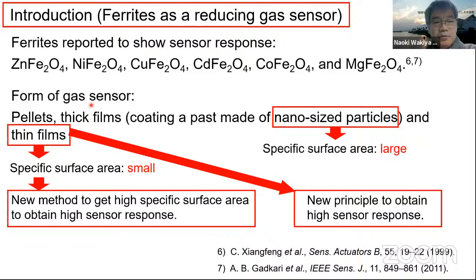And ferrites are reported to show sensor response, such as zinc ferrite, nickel ferrite, copper ferrite, cadmium ferrite, cobalt ferrite, and magnesium ferrite. As forms of gas sensors, there are sintered pellets, thick films, and thin films. A thick film is synthesized by coating a paste made of nano-sized particles. In the case of nano-sized particles, the specific surface area is large. In the case of thin films, usually the specific surface area is small.